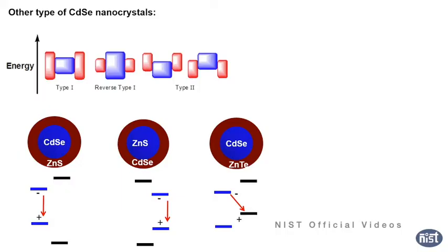So there are many kinds of nanocrystals that people found later, like core-shell. Generally the core-shell is cadmium selenide and zinc sulfide shell. It's called type 1, meaning the zinc sulfide has a large band gap and covers the lower band gap core, so it's a stable emission. You can see the separation between the electron and hole, so it cannot go to the outside. Sometimes when it's in a solvent like hexane or toluene, there is some moisture, which can destroy your nanocrystal and create a trap. If you coat with zinc sulfide, it cannot be trapped, so the emission will be more stable than the naked one.